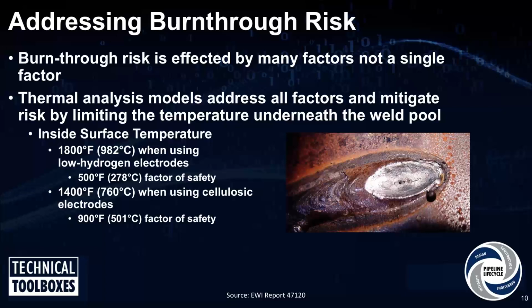On the other side, if you have a limit of say 1/8 inch wall in your welding manual, a welder might think, well, if I'm welding over 1/8 inch wall, I don't have to worry about burning through at all, which is also not the case. Because if the welder welds too hot, you can still burn through pipe over 1/8 inch wall. I've seen burn-throughs as thick as a 1/4 inch wall. Now it's very rare, and typically the welders might be welding a little hotter than they should have been, but it is possible. But again, it goes back to you have to control all the factors to really determine what is an acceptable risk.